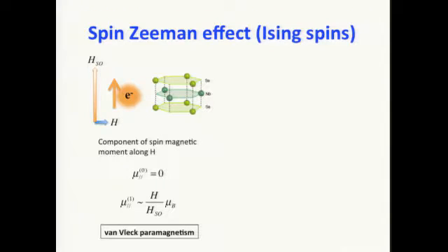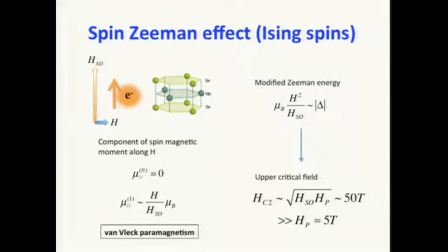But then if you go one order higher, the applied magnetic field actually competes with the spin-orbit field. That gives rise to something called Van Vleck paramagnetism, which is the magnetic moment induced by the external magnetic field. So the magnetic moment can be written down in this form, H over H_SO times the Bohr magneton, mu_B. So now the Zeeman energy gets modified to this form. Instead of being proportional to H, it's actually proportional to H squared, because the magnetic moment is induced by the magnetic field. When this energy becomes comparable to the superconducting gap, superconductivity is destroyed.